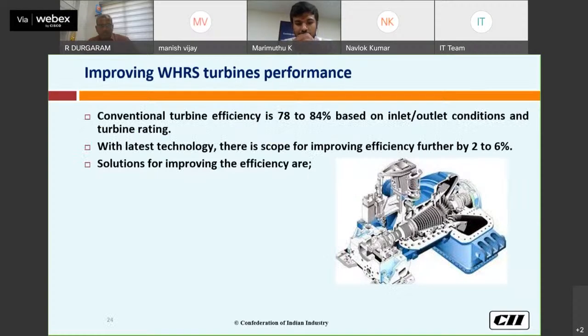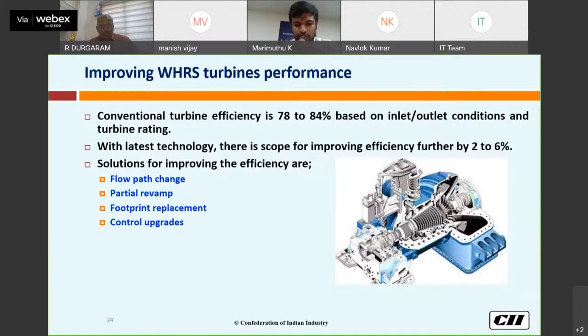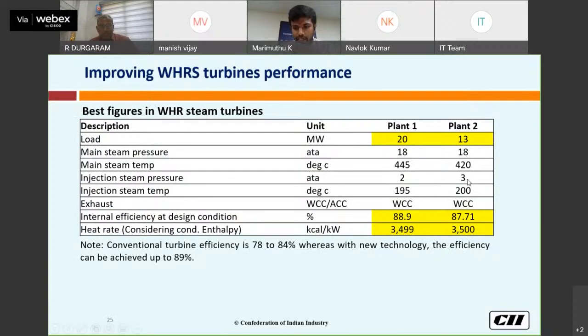Conventional turbine efficiency is around 78 to 84 based on inlet and outlet conditions. So with the latest technology, there is scope for improving the efficiency, either by flow path change, partial revamping, or foot print replacement, or with a control upgrade. So 2 to 6% efficiency improvement is possible in the existing turbines. This is based on the study, some of the best figures: the heat rate and internal efficiency of the turbine. Conventional turbine is around 78 to 84, while with the new technology, turbines are available with internal efficiency of 88 to 89. The heat rate is also around 3,500 kilocalorie.